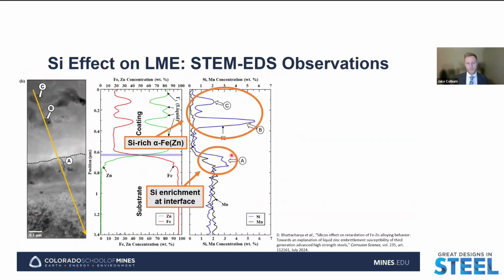And of noticeable concern here, when we look at the silicon concentration across this line, we see a noticeable enrichment of silicon at the interface that is above that of the bulk composition. So again, if our bulk composition is around 1.5 weight percent, we see an increase of that up to roughly 3 to 4 weight percent at the interface.